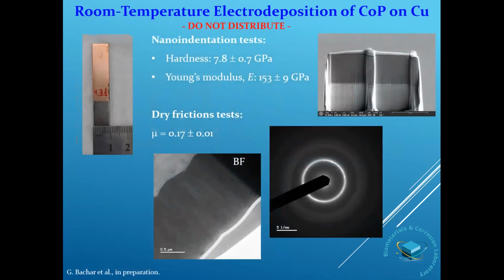Here you can see the macroscopic appearance and uniformity of the cobalt phosphorus coating on copper. The coating has excellent mechanical properties, as you can see here: high hardness, high Young's modulus of elasticity, and surprisingly low coefficient of friction. The coating could not be scratched from the substrate using a diamond scalpel blade. In a standard adhesion test, the samples failed within the glue, and neither cohesively within the coating nor adhesively between the coating and the substrate.